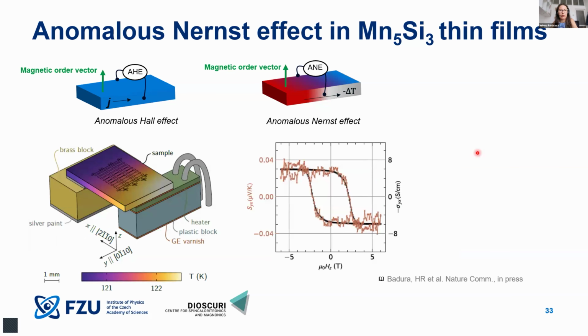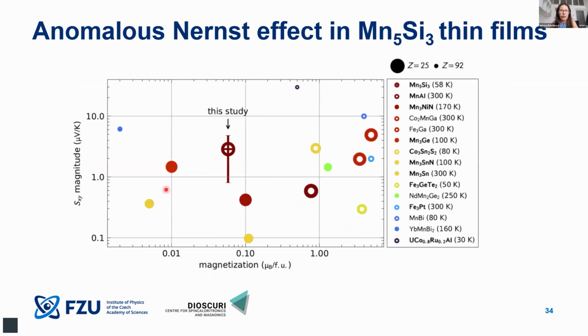And when we already had our Mn5Si3 available, we patterned the devices which we know work for the anomalous Nernst measurement, and put them on a setup where we generate a thermal gradient propagating along the full substrate. By generating this thermal gradient, we can pick up the thermoelectric voltage. Here you can already see in orange the signal which we measure. So the anomalous Nernst effect is indeed present. It agrees very well with the anomalous Hall effect, and it has a spontaneous character. We can also quantify the thermal gradient and compare the anomalous Nernst effect with the existing literature, with the full spectrum of materials ranging from antiferromagnets to ferromagnets.